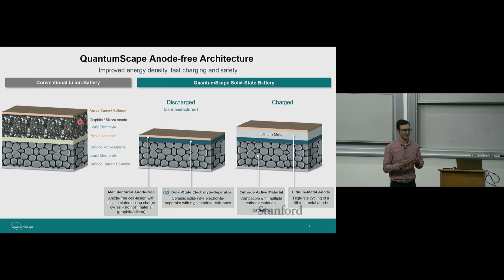So this reaction consumes both the electrolyte and lithium in ways that degrade the battery's performance. So we've, again, replaced this liquid electrolyte and the porous polymer separator with a solid that's then compatible with lithium metal. By doing that, we've hoped to solve these two main challenges. We didn't invent the concept of a solid-state electrolyte either. Many other groups have been pursuing that for decades.